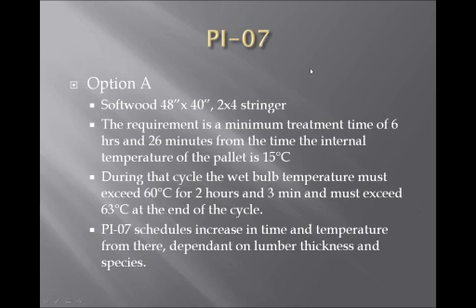Under option A, the minimum required heat treatment time is 6 hours and 26 minutes from the time the initial core temperature of the pallet is 15 degrees Celsius. Meaning if you're going to start your charge in January and your pallets are stored outside and they're -5, you're still going to have to heat that pallet load up until 15 degrees Celsius before the 6 hours and 26 minutes commences.